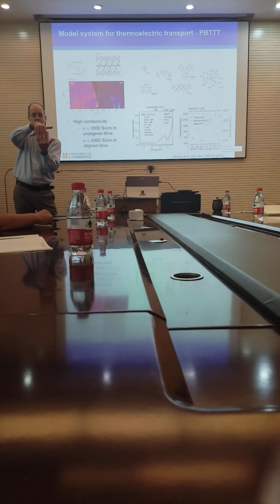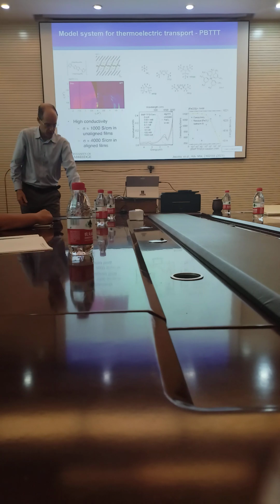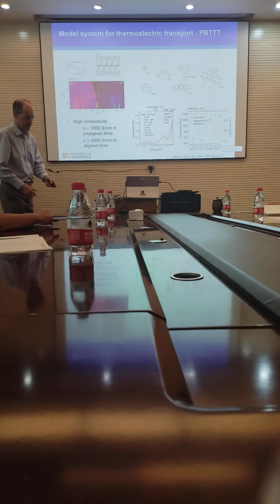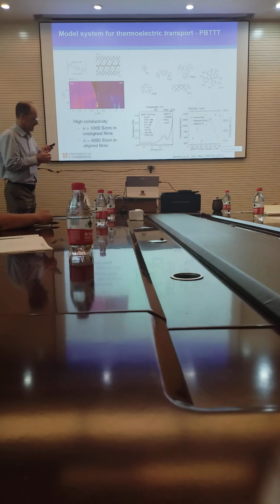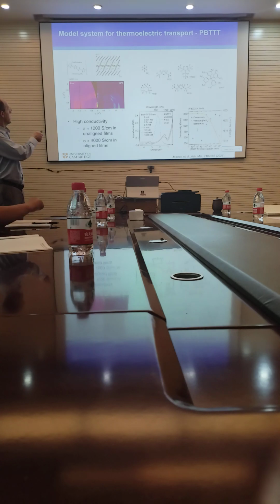And when you dope the material, essentially what happens is that the interdigitation opens up a little bit, and that defines a little molecular cavity, and you can incorporate the counterions into that molecular cavity. And then you can see a little cartoon here. So this is this cavity here, and the ionic liquid anion fits into this cavity right next to the polymer backbone.